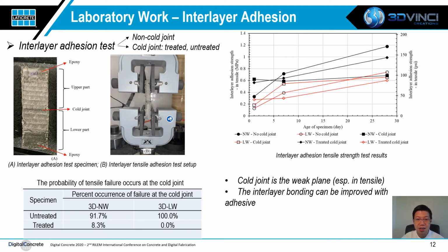When the cold joint exists and it is not treated, most of the time the failure plane occurs at the cold joint. However, treating the cold joint using adhesive improves the interlayer bonding strength of the cold joint. This can be seen from the reduction of the percent of failures that occur at the cold joint when it is treated.